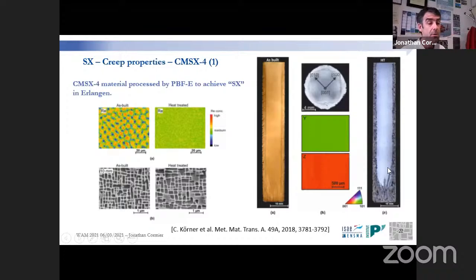Bridgman casting: to establish an almost vertical thermal gradient during processing. So a very hot process overall. They are obtaining a very, very small dendritic structure with primary dendrite arm spacing of typically 10 to 20 microns. That means you can then do solution treatment at lower temperature or shorter durations. And they have been able to obtain a microstructure very, very similar to a conventionally processed single crystal.